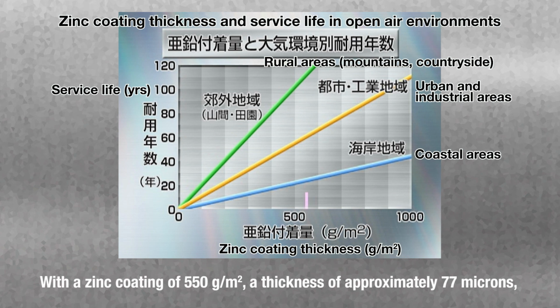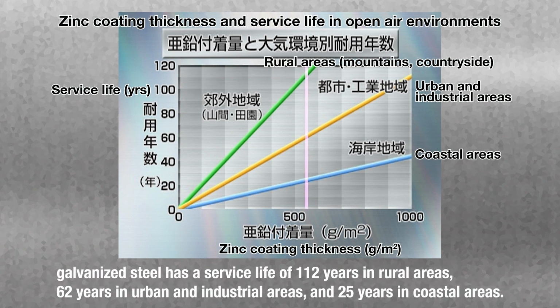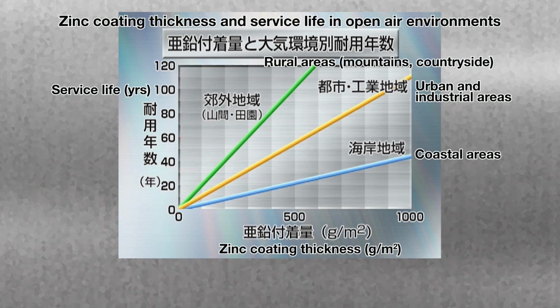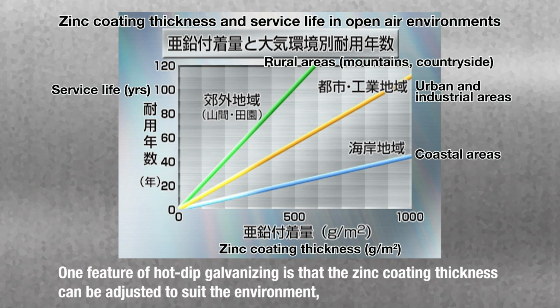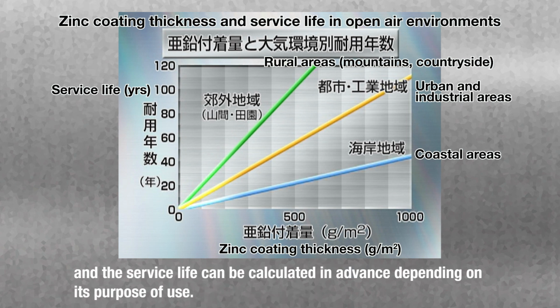With a zinc coating of 550 grams per meter squared, a thickness of approximately 77 microns, galvanized steel has a service life of 112 years in rural areas, 62 years in urban and industrial areas, and 25 years in coastal areas. One feature of hot-dip galvanizing is that the zinc coating thickness can be adjusted to suit the environment, and the service life can be calculated in advance depending on its purpose of use.